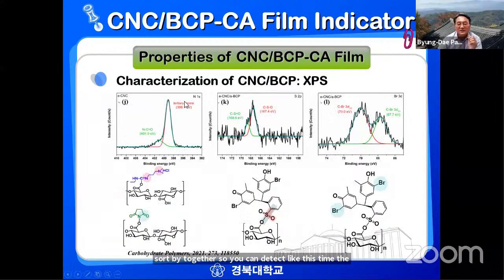We also have the nitrogen spectrum here, the N-C-O, the amino group right here. This is the CNC over here, and EDC, and the reactive cellulose, and the NHS, EDC, with the reactive CNC here. And also it's the ECNC with activated BCP sulfur. We have sulfur like this, and the reacted sulfur groups here. And an interesting thing is the bromine peaks right here. We have ECNC and activated BCP and the bromine, and two peaks. One is reacted here, the other one here. That means these bromocresol purple molecules are reacted at the CNC surface.